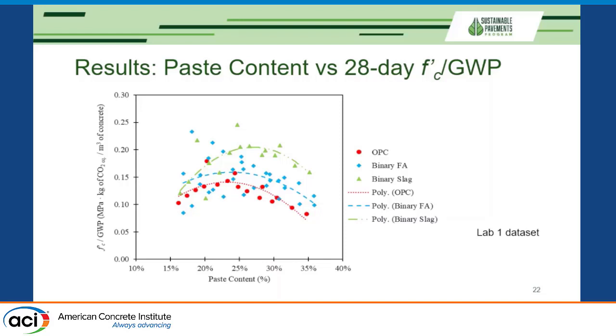So here we are showing the effect of paste content on the composite parameter, that is compressive strength over global warming potential. That means how much pollution are you creating to create 1 unit of compressive strength. Higher values are better because it means you're creating high strength with minimum pollution. This is only from Peter Taylor's CP Tech Center dataset, because they have played with paste content. We can see that these different mixes have different optimum points, but they are all around 25% or so, which coincides with the AASHTO recommendation. So we know that there is a point of trade-off where you are adding more and more paste, but you're not achieving anything in terms of compressive strength, so why don't we just stop here in the middle?